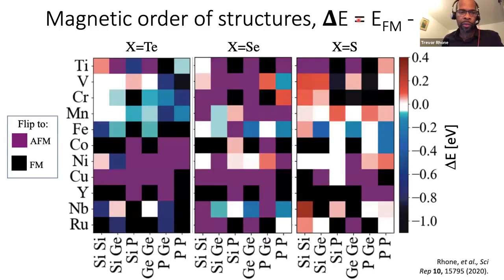So I can calculate this value of delta E and display the result. This is for the tellurium, X equals tellurium, on the left panel. Center panel is for selenium, and on the right is just for sulfur. And the horizontal axis are the B site substitutions. The vertical axis is the A site substitutions, and the color represents this value for delta E. So chromium germanium telluride sits on this square right here. Each square represents a different crystal structure.